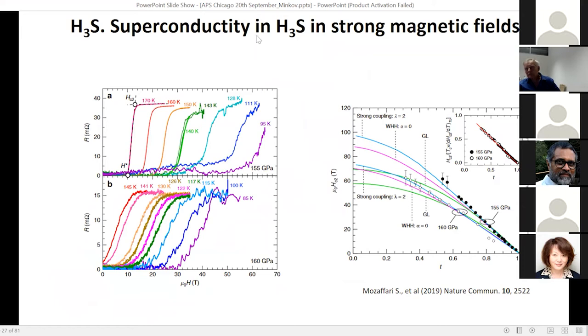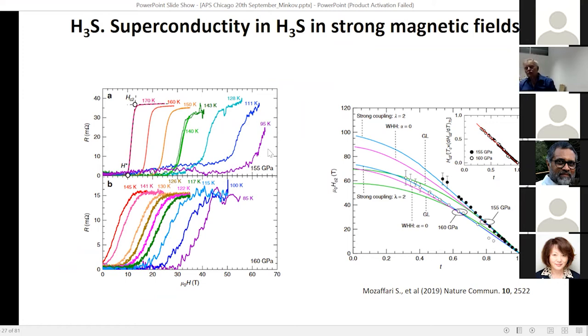We also studied superconductivity in strong magnetic fields. Magnetic fields up to 65 tesla were applied in pulsed mode. The small cell was also very useful for pulse measurements — and this was a record measurement at 45 tesla in the strongest magnet in the world at Tallahassee. We cannot fully suppress superconductivity — that would require about 100 tesla — but we can extrapolate reliably to obtain the upper critical magnetic field Hc2.